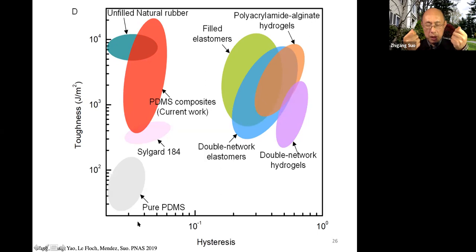People play with PDMS. PDMS has a very low hysteresis, less than 10%, a few percent. But pure PDMS has very low toughness, about 100. By making stiff and soft PDMS, making it a composite, you easily lift up the toughness as high as natural rubber, once again. And this material is fatigue resistant because it's an elastic dissipator.